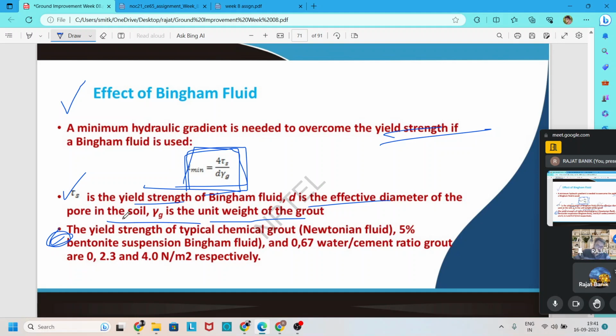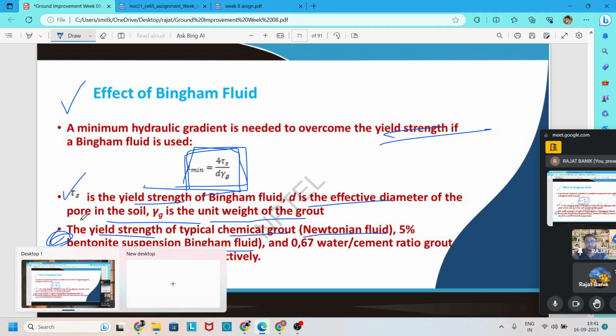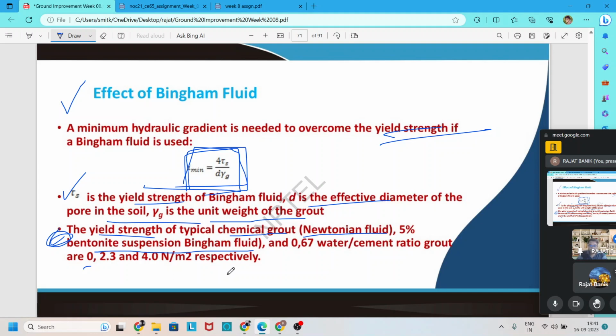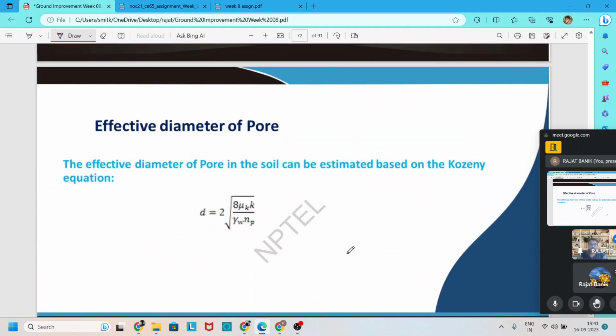That is for chemical grout, where in most cases it is a Newtonian fluid, the yield strength is 0. And for bentonite suspension, which is nothing but a Bingham fluid, the initial yield strength is 2.3 Newton per meter square, and for 0.67 water cement ratio, the yield strength is 4 Newton per meter square respectively.